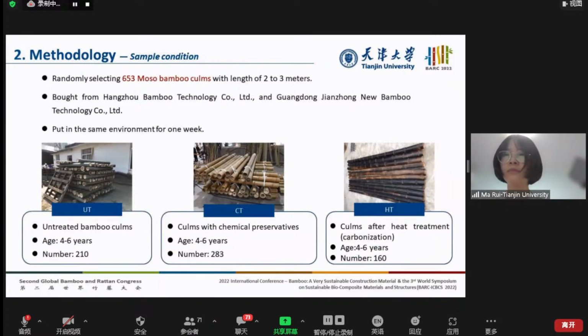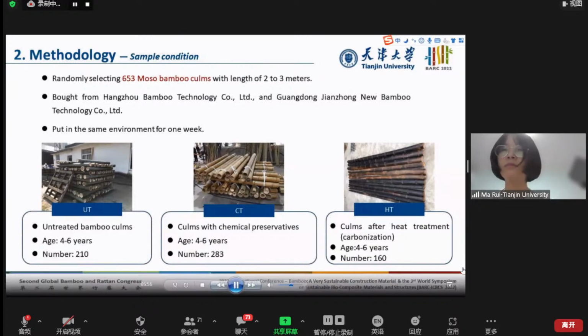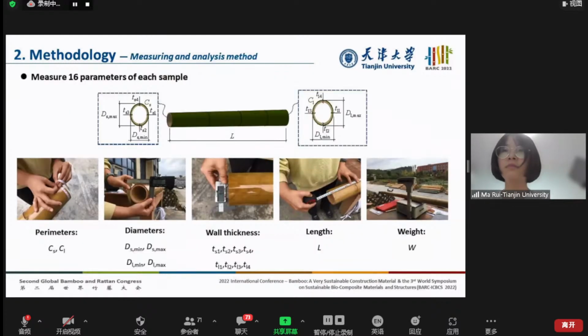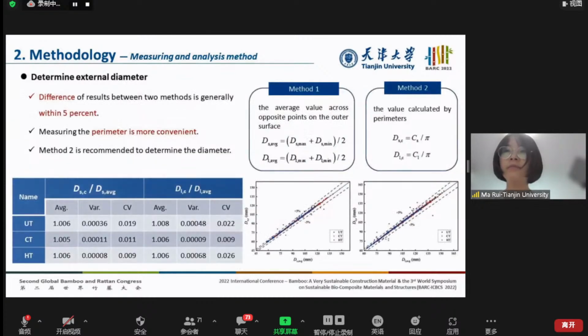All of the bamboo culms were put in the same environment for 1 week to avoid the influence of the environment. Length and perimeter were measured by the tape, while the external diameter and thickness were measured by the vernier caliper, and every culm was weighed by electric scales. The external diameter of each end was determined in 2 ways, one of which is the average value of 2 perpendicular measurements made across opposite points on the outer surface. Another is calculated by perimeter.